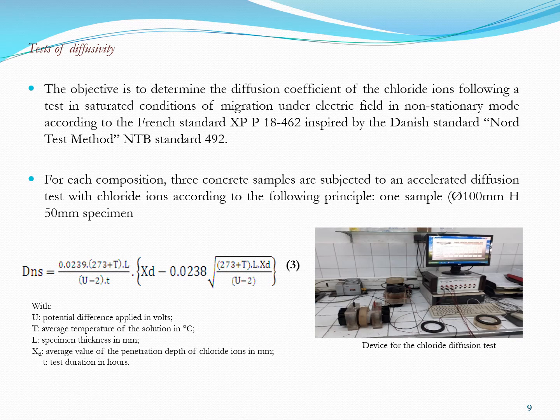For the diffusivity, the objective is to determine the diffusion coefficient of the chloride ions following tests in saturated conditions of migration under an electric field in non-stationary mode according to the French standard. At the end of the test, the sample is cut parallel to its axis. The section is covered with a silver nitrate solution in order to determine the depth of penetration of chloride ions.